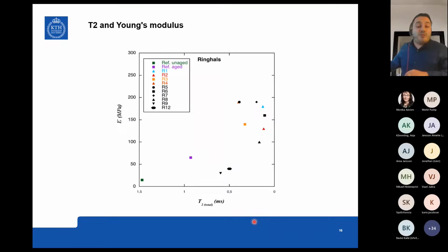This is some Young's modulus data. So again, we see the same trend here. So as I mentioned earlier, much higher signal for the pure rubber samples, reference sample of cable, still giving you a higher T2 time, lower modulus compared to these samples which have been in the field. So preliminary, we are seeing something positive here, I would say, but we are still really, really low in TRL, so we need to do a lot more.